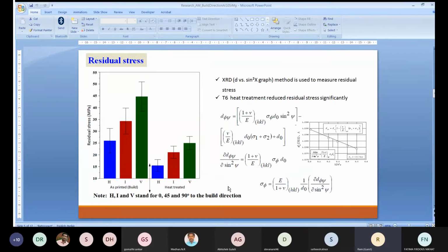Okay, so how do we measure the residual stresses? We have used the X-ray diffraction method. In X-ray diffraction there is a method called the d-spacing versus sine square psi graph. Here psi is called the tilt angle. Okay, we keep the sample in the XRD machine, and